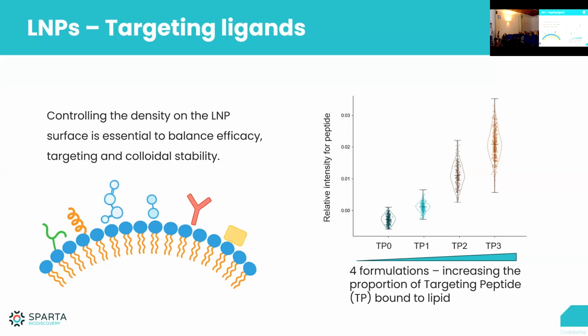And maybe about 80% or so of the particles here had the targeting ligand, and you can draw a line in the software to actually quantify that. And then they were adding more and more targeting ligand. I just want you to imagine if you just got the mean values here, and no error or no other part of the graph, because that is what a bulk technique would give you. It would give you a standard deviation, but the standard deviation has nothing to do with the variation within your particles. It has something to do with the measurement variation of how accurate your HPLC is to reproduce the same value, rather than saying anything about how variable these particles are.